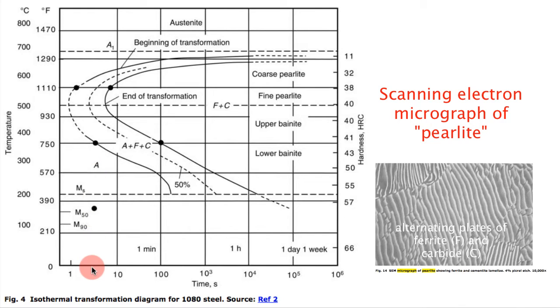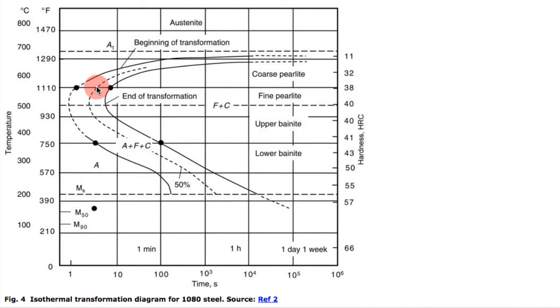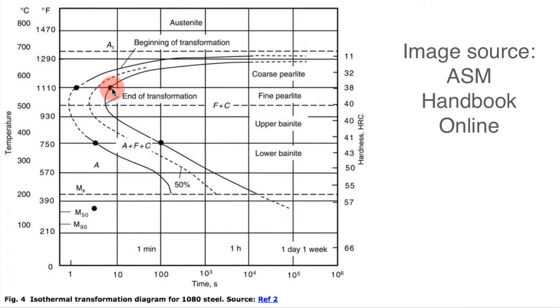When I say here, what I mean is you could take this down to the timeline. So within seconds, it would start the transformation to pearlite—this is a log scale. This is about, I would say, three seconds. This is a little over one second. This is about three or four seconds when it's halfway done, and probably at eight seconds